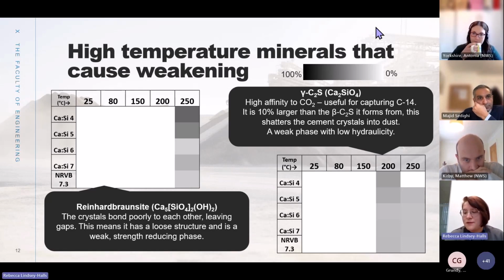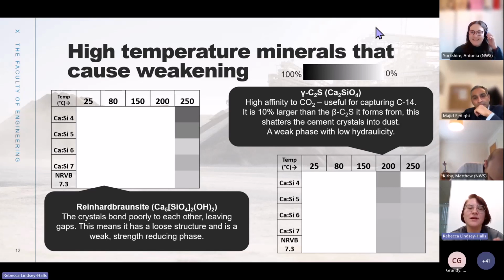In the lab, I've also observed that above 150 degrees, the cements are incredibly weak to touch. At 200 degrees, I have to be careful picking them up with tweezers because sometimes they just go poof and you just get a dust. And at 250 degrees, they're actually too weak to handle. So to get other measurements where I want to look at the porosity, I have to cure them in special tiny molds that can be fitted into the machines.